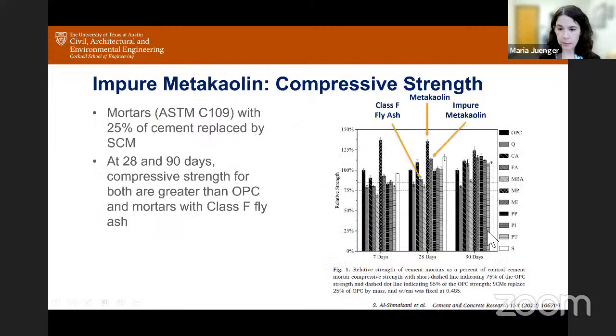Again, if we look at compressive strengths, this is the same plot shown earlier, just looking at the metakaolins in these. So the metakaolin at 28 days is significantly higher than the fly ash and the OPC, and even the impure metakaolin is higher than both as well. So these materials are certainly sufficient and adequate for replacing cement in concrete, and will provide good performance.